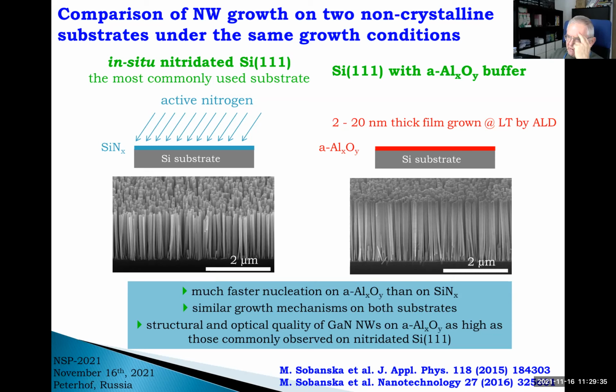So in general terms, we want to understand how the growth process on such amorphous substrates takes place. For that, in my talk I will compare two systems. One is a silicon substrate which is exposed to active nitrogen, so the silicon nitride film is formed. This is a standard substrate used for MBE growth of gallium nitride nanowires. And the other one is a silicon substrate with a thin film of amorphous aluminum oxide that was deposited on the silicon by atomic layer deposition.